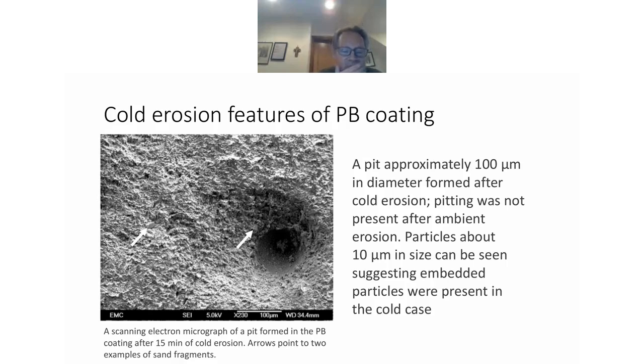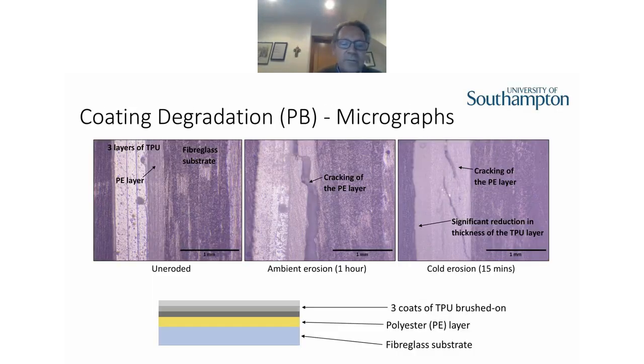If we look at the brushed polyurethane, the 3 layered on top of polyester system, there were some quite dramatic pit features here, and also you could see some either fragments or embedment of small particles in the system, in the actual coating. But you've got quite concentrated loss of your coating, which is obviously undesirable here. But you do get some embedment, which will affect the mass loss. You sort of get a mass gain because you've caught sand in the system.